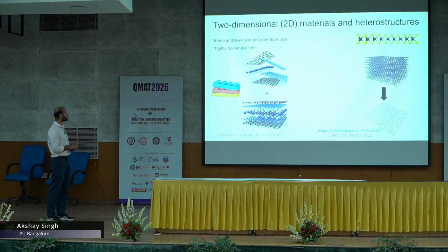The thing that we're interested in is that they have tightly bound excitons. Excitons are electron-hole Coulomb-bound pairs, and what's interesting in 2D materials is that the exciton binding energy is so strong that they are present even at room temperature. That's why the field started in about 2010 and has just exploded after that.